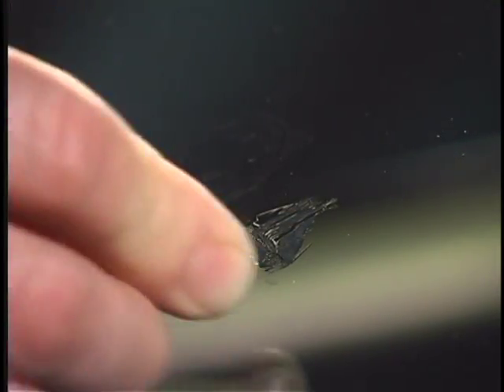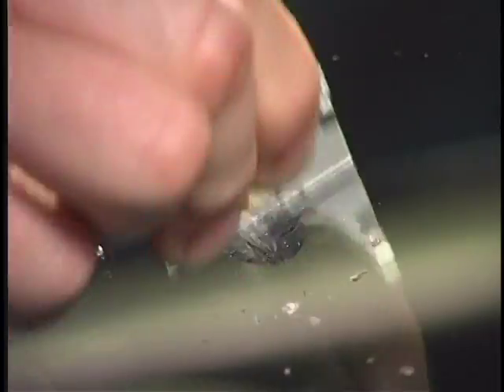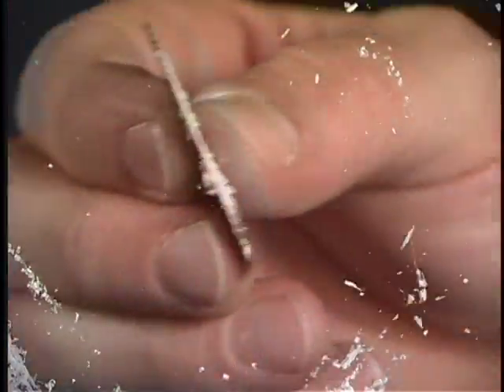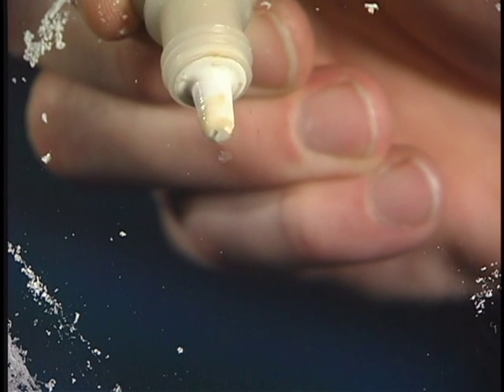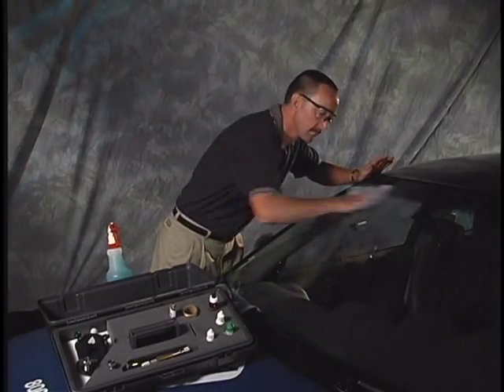Remove the excess resin by holding a sharp razor blade at a 90-degree angle to the glass and scraping back and forth across the surface of the resin until completely smooth. If it is not completely smooth, reapply resin and repeat the curing process until satisfied. Place 1 drop of pit polish on the center of the repair and polish with a clean paper towel for 30 seconds. The result should be a professionally repaired windshield that looks at least 80% better and is restored to the strength of the glass around it.